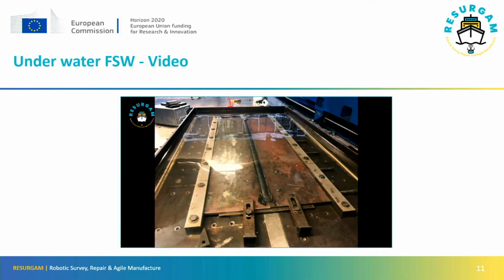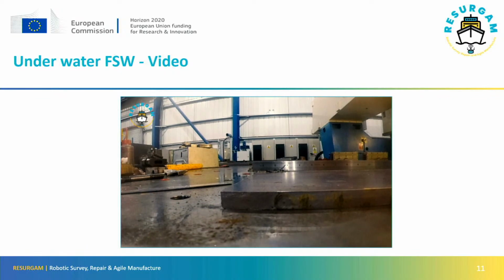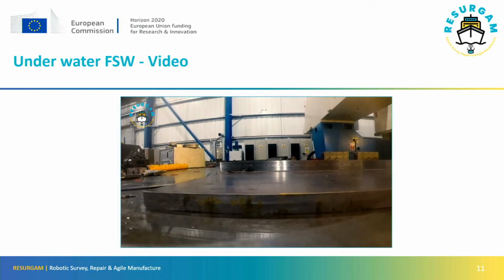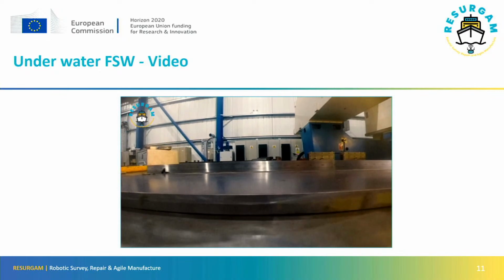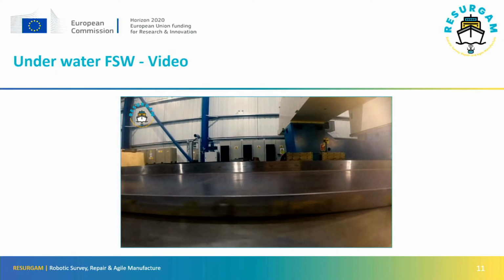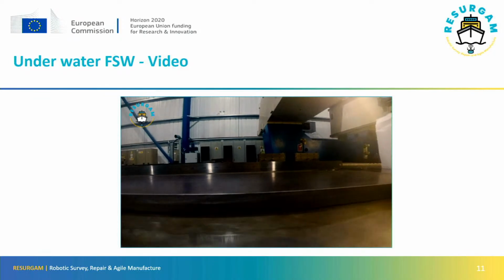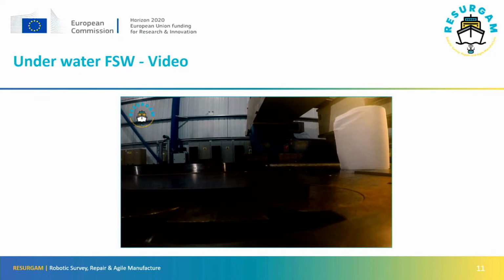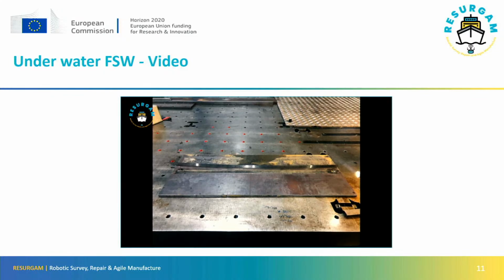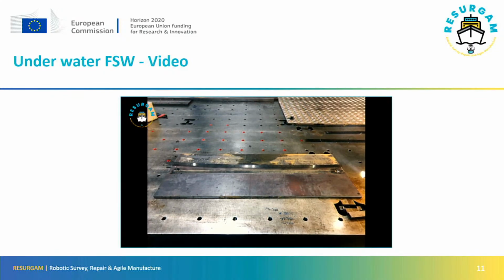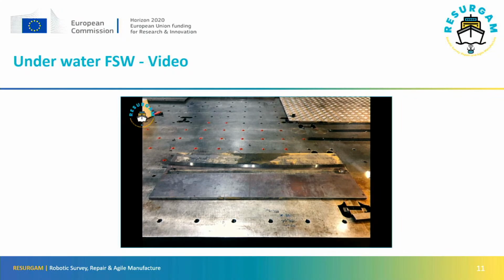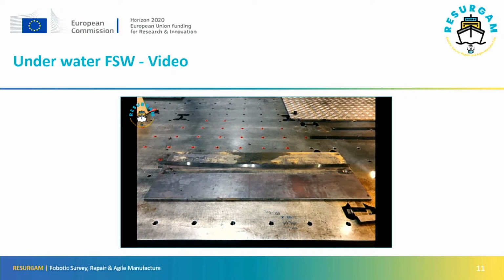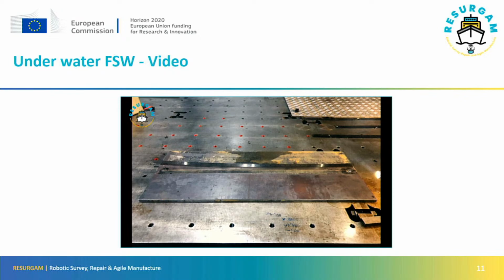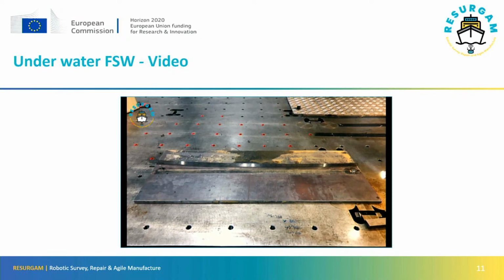As can be seen, the weld is smooth and free from spatter. The lack of distortion allows a 1 metre long steel rule to be balanced on its edge along the plate. A section cut through the weld shows it to be defect-free, with a fine-grained wrought microstructure. It is therefore perhaps unsurprising that tensile test pieces cut from the welded plate show the weld to be stronger than the original steel, all tensile failures occurring in a ductile manner outside both the weld and the heat-affected zones.